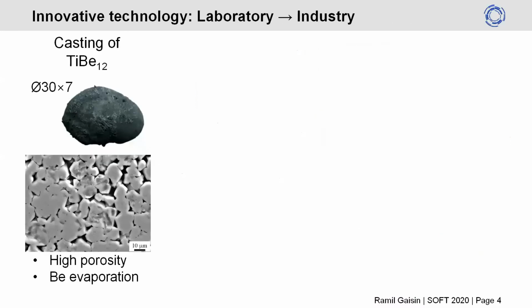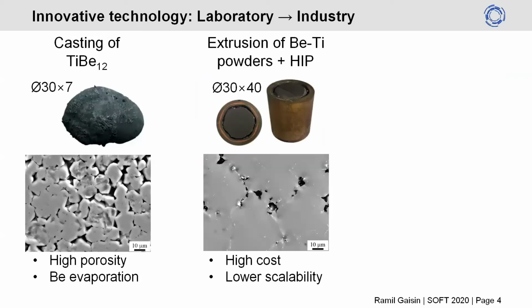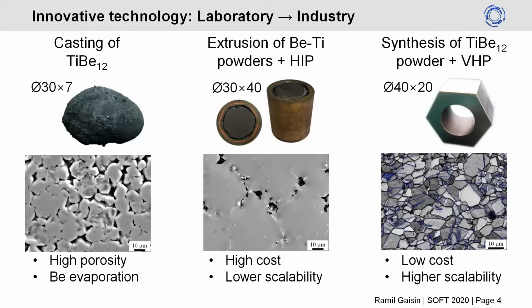Since beryllide is a very hard and brittle material comparable to gemstones, its manufacture has faced many challenges. Conventional casting resulted in high porosity and excessive evaporation of beryllium. Powder metallurgy route with extrusion and hot isostatic pressing provided high-quality fine-grained material, but the use of capsules made the technology too expensive and low scalable. And the third way, based on vacuum hot pressing of already synthesized beryllide powders, led us to success.